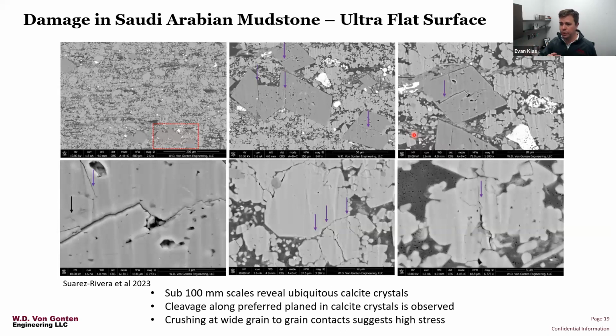Moving on to the mudstone from the Middle East, we saw a different story. Taking a closer look at the grains and the damage sample, we start to see the manifestation of that stress clearly. You can see in these blue arrows a lot of fractures occurring within those dolomite grains, mainly along preferential planes.